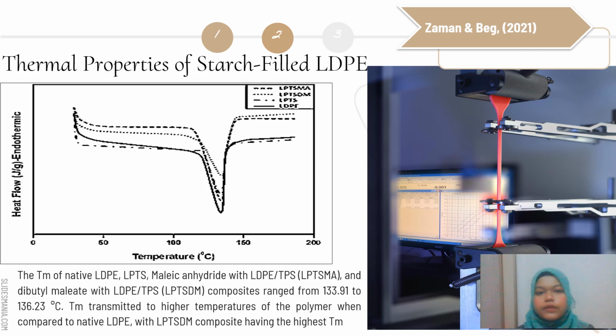According to Zaman and Beg 2021, they analyzed the thermal properties of LDPE TPS, which is LPTS composite. In this figure, DSC endotherms reveal a very slight change in the crystalline form of the matrix, indicating that melting temperature, which is TM in this study, was dependent on compatibilizer and plasticizer. The TM of native LDPE, LPTS, LPTSMA, and LPTSDM ranges from 133.91 to 136.23 degrees Celsius. TM shifted to a higher temperature of the polymer when compared to native LDPE, with LPTSDM composite having the highest TM.